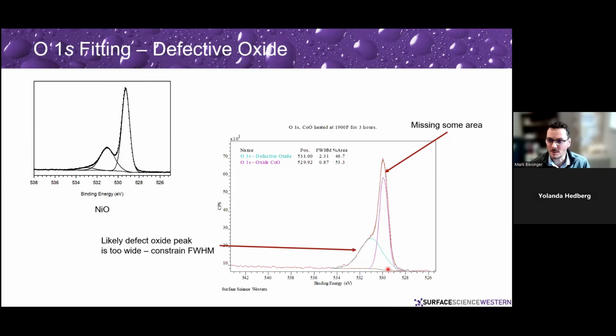So this still might be some defective oxide, but you can see how this peak is really broad. And so it's kind of stealing peak area from this main peak. Like this main peak really should be up here. And so you've got to put some constraints on. You can't let this peak get too broad. So you put some constraints on the thickness of this peak. Otherwise, you're really not getting the true picture here.